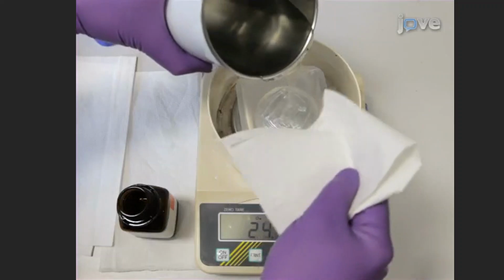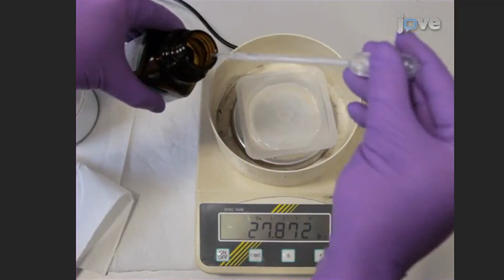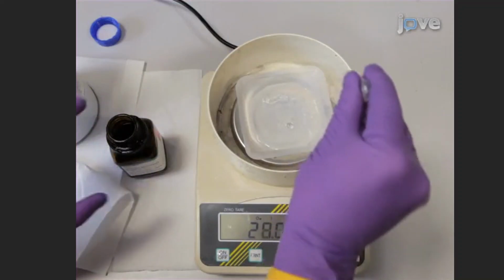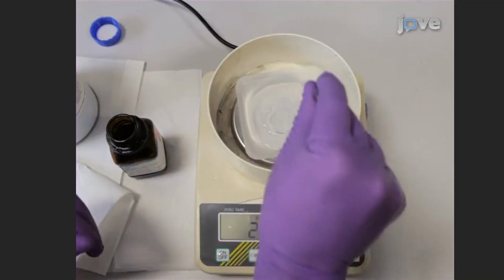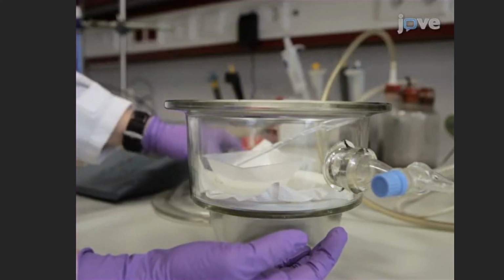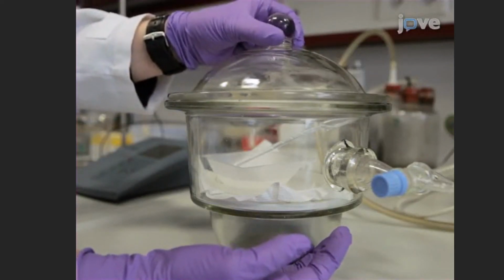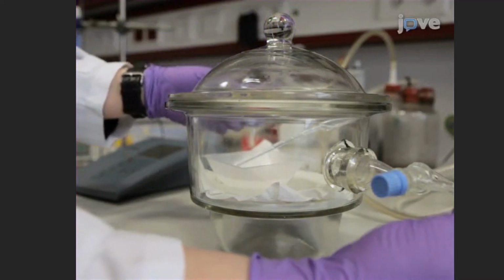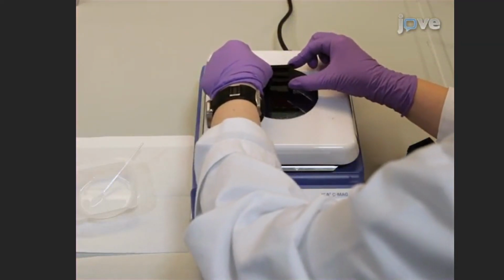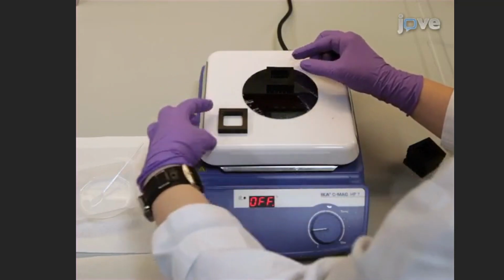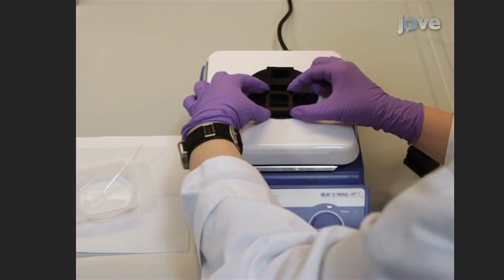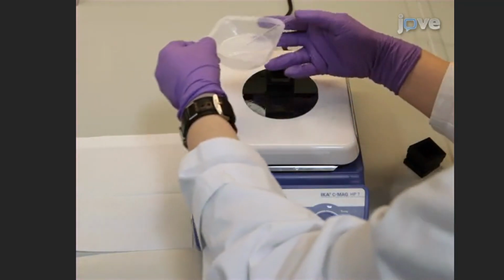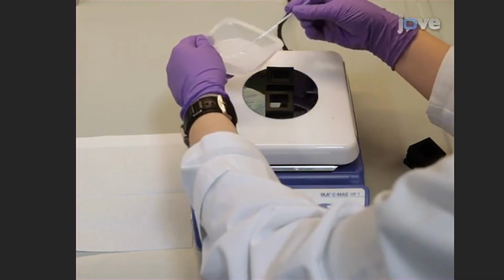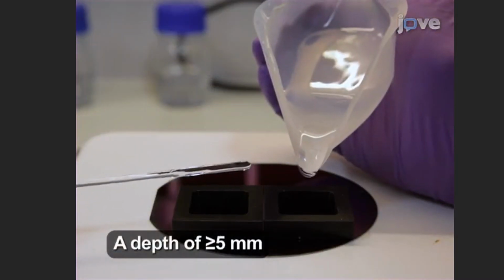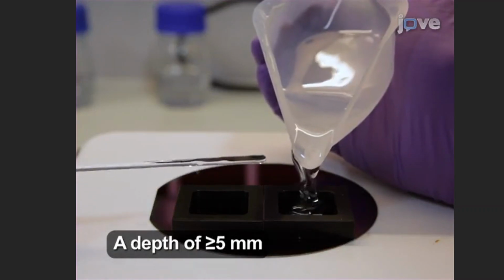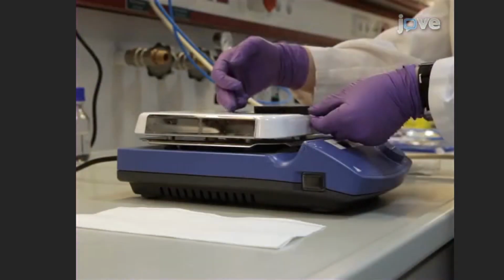Begin the procedure by mixing the PDMS pre-polymer thoroughly with the curing agent at a ratio of 10:1. Next, degas the mixture in a vacuum desiccator for typically 20 minutes. Then, place the two-layered microstructured SU8 wafer on an 80°C hot plate and align the polymer frames to each device on the wafer. Pour PDMS into the frame and allow 1 hour to ensure complete thermal curing.